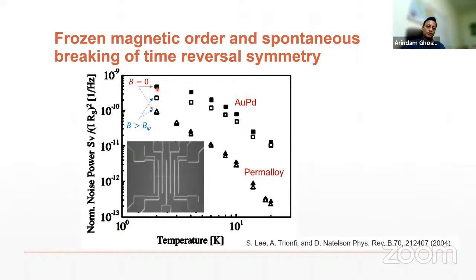However, if I take a permalloy wire, which is a magnetic system, you can see even if I apply a magnetic field, the noise does not change because the time reversal symmetry in a magnetic system is spontaneously removed even at zero magnetic field. And hence, applying a small magnetic field does not make any difference. So we use this concept to look at the magnetism in graphene grain boundaries.